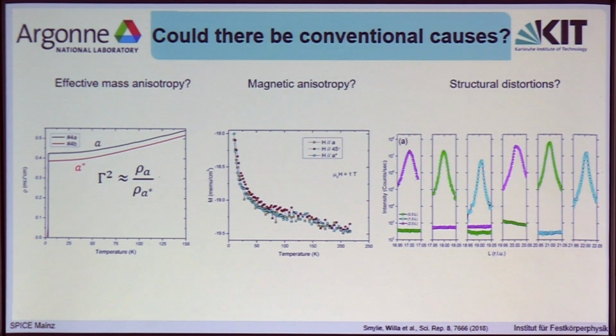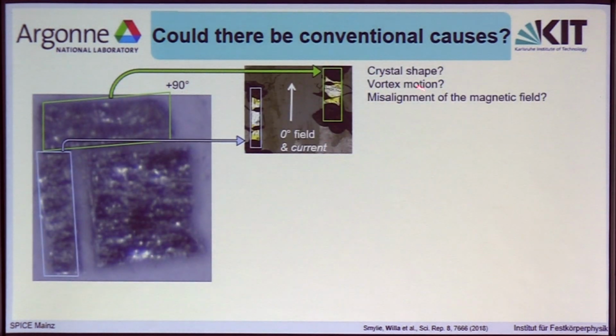Now, another thing that came up is whether it could be due to the crystal shape, the vortex motion that is induced by the current flow, or misalignment of the magnetic field in the plane. And we wanted to come up with an experiment that could disprove this. And what we've done is the following. So we took a large crystal of strontium-doped bismuth selenide. We cut 2 crystals out from it, which have about the same shape ratio. And we put them at a 90-degree angle, and we positioned those next to each other on the same substrate. So they have the same current direction, the same shape, and they will have the same field in the cryostat.